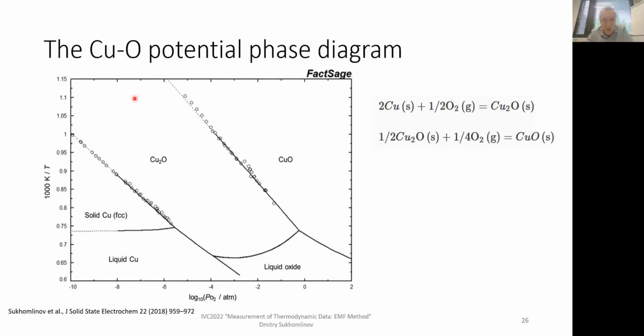But before we go there, let me show you this copper-oxygen potential phase diagram. No alumina here, just binary. All those open circles are our measurements superimposed on the calculated FactSage potential phase diagram, temperature versus oxygen partial pressure.